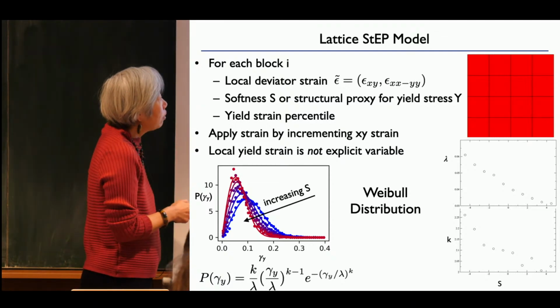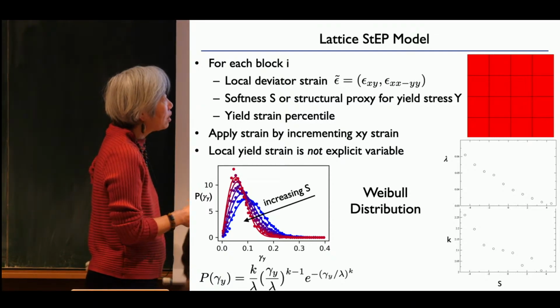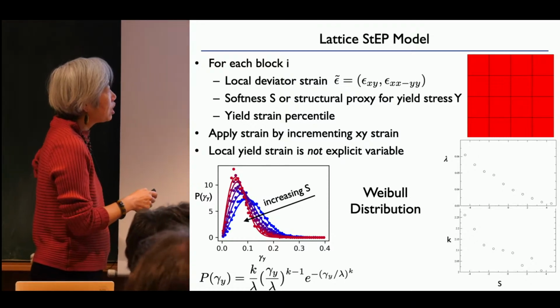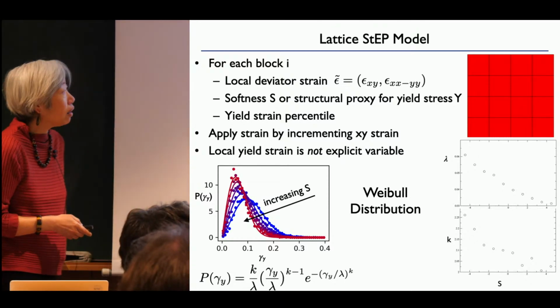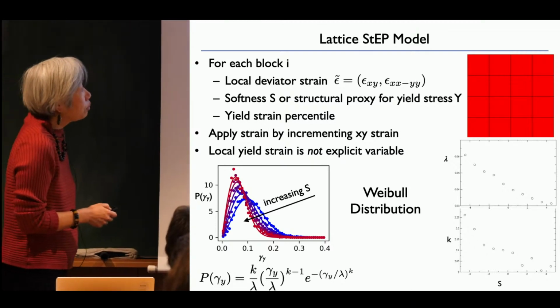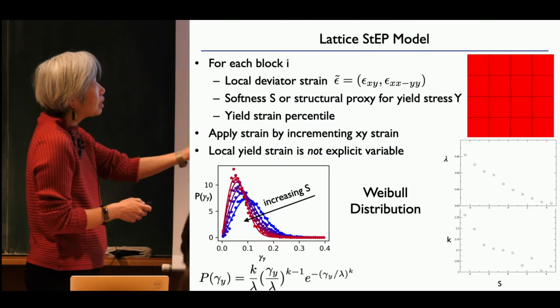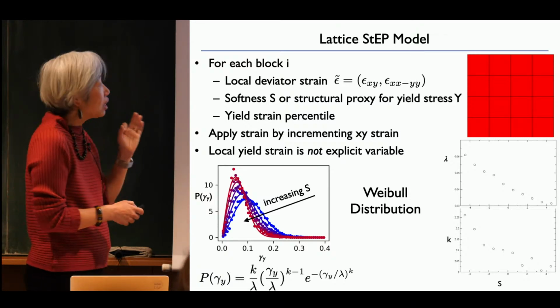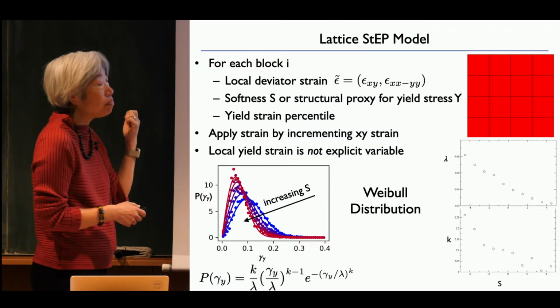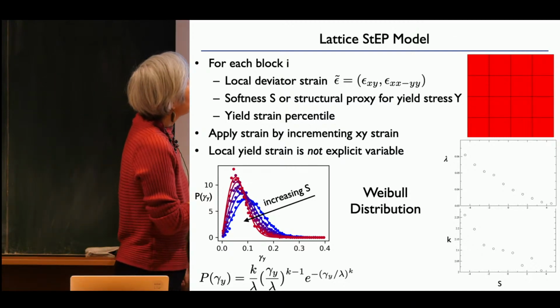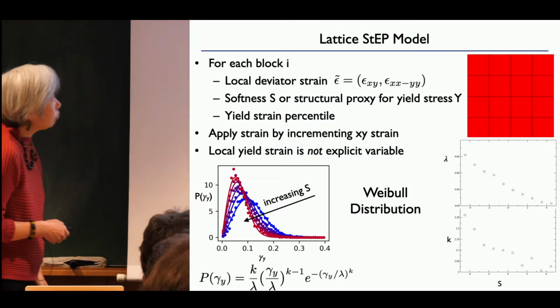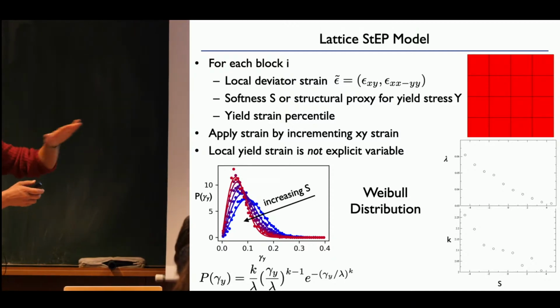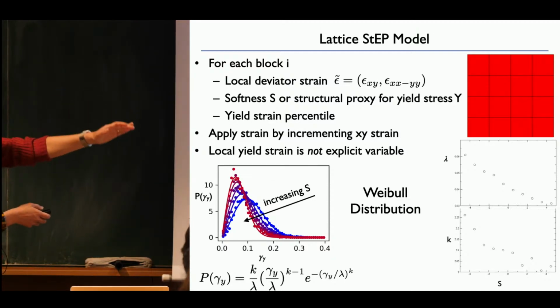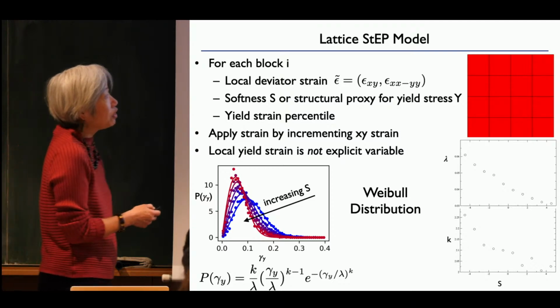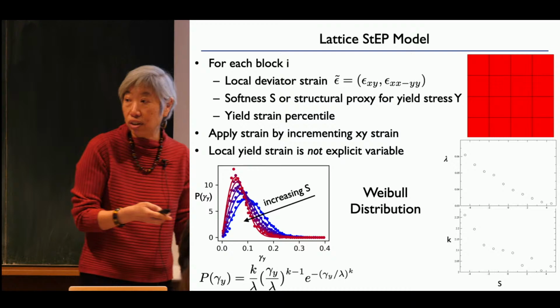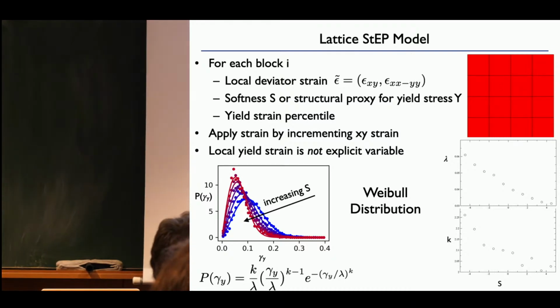Whereas particles with a very low softness, which are much less likely to rearrange, have a yield strain distribution that's quite different. So basically, for each block, we assign a yield strain percentile. Which percentile in this distribution is random, but the softness determines the distribution. And then we apply strain by incrementing the xy strain, as usual. The local yield strain is not an explicit variable. It's softness, the structural proxy for the yield strain, that we use.